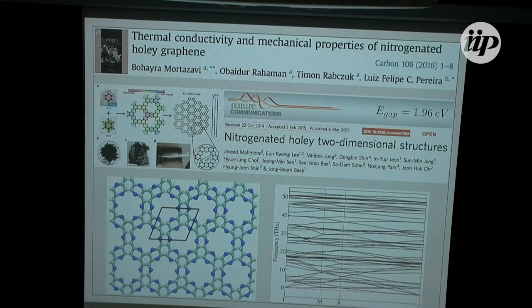So the next point we added was from nitrogenated holey graphene. The authors didn't really call it nitrogenated holey graphene, they call it nitrogenated holey two-dimensional carbon structures. Now, these people actually produced this in the lab. This is produced via wet chemistry, and it's a structure where you have a bunch of hexagons, but some of them only have carbon atoms, and some of them have carbon and nitrogen atoms. The phonon spectrum of this thing is here, so we see no negative frequencies that Hugo was so worried about. So we know that our potential works for this material. This is a new material. In principle, the potential didn't have to work, but it does.